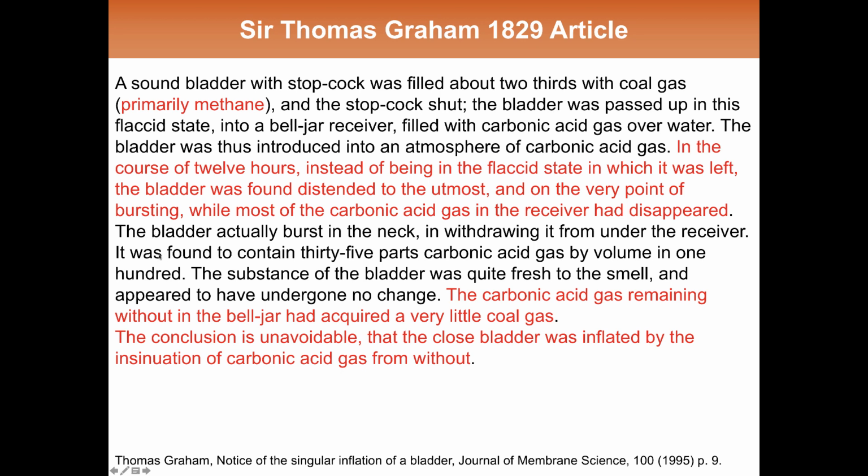He found that inside his balloon or his bladder, which had mainly methane to start with, it had in the end 35 parts by volume of carbon dioxide. There's no carbon dioxide, or almost no carbon dioxide in that balloon at the beginning. And he investigated his balloon material, which seemed to be quite fresh to the smell, and appeared to have undergone no change.